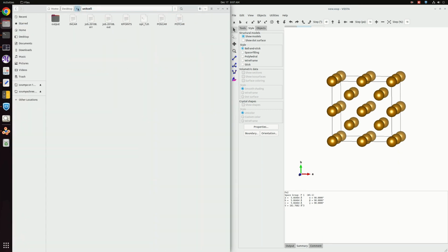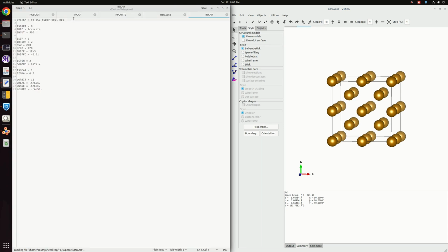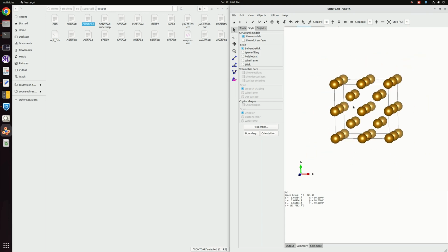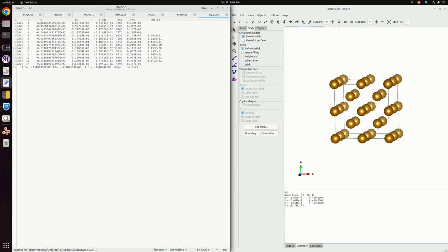Now this is done. Here I have optimized the supercell with the same input, and you can see the INCAR tags are exactly similar. Only the K point value has changed. Initially the K point value was 15 15 15 and now the grid is 7 7 7, because as we have elongated the cell, similarly we have to reduce our K space values. After that I got the result for the supercell, and this is a very quick calculation; within just a single step I got this optimization. So just a single SCF calculation was done to get this.